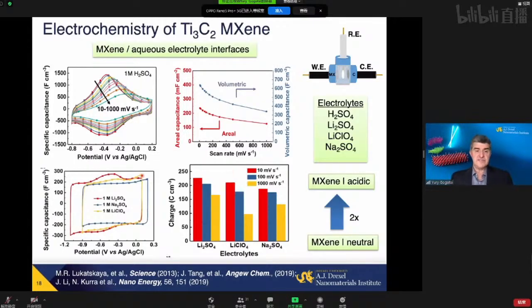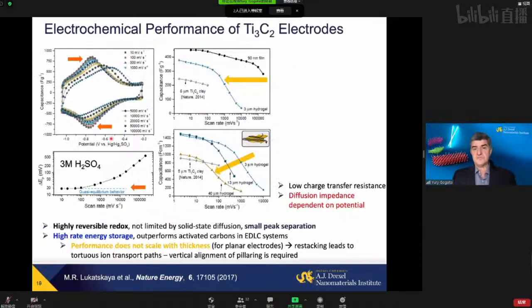What we find there, if we take some of the salts, for example, sodium sulfate, is cyclic voltammograms which are perfectly rectangular, very much resembling those of a carbon double-layer capacitor. So we assume probably no redox. But in a protic electrolyte, you will see peaks which are electrochemically reversible, but shift slightly, and the separation increases as we increase the rate, getting high volumetric capacitance. So the first message is that different ions give you different processes here.